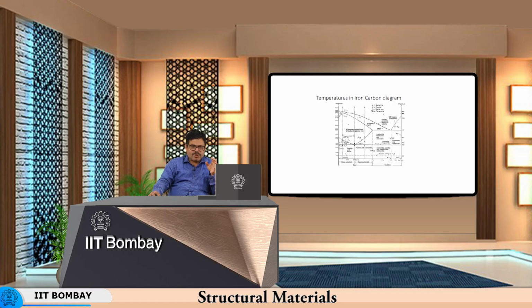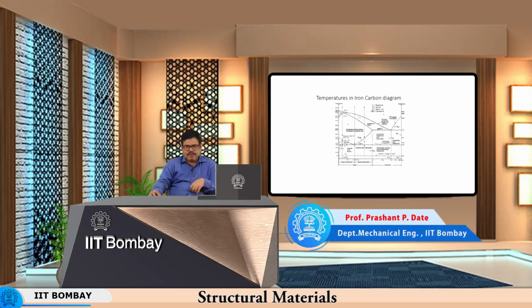So, here it is not very strong, since you want to deform the material, you do not need it to be very strong either, but then in service you need it to be strong. So, naturally what you do is that from austenite you tend to cool it very rapidly to what you call martensite. Now, this is based on a very slow cooling rate, but formation of martensite happens at a much faster cooling rate. So, you will not see any martensite over here, but then if you were to adopt very slow cooling rates, then you will get different kinds of microstructures depending on how the material has been cooled, at what cooling rate it has been brought to the room